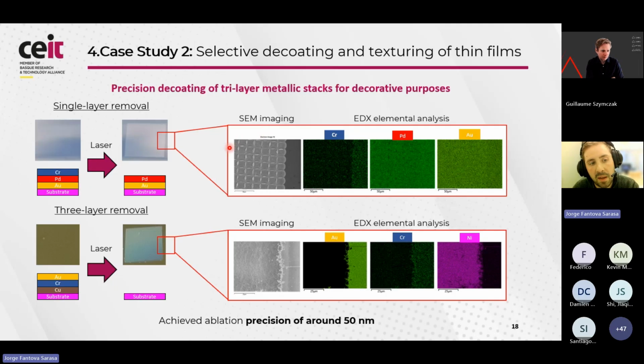And through this electron microscopy analysis, the imaging and the elemental analysis by EDX, in this case we achieve decoating of only the topmost layer, leaving the palladium and nickel layers unaffected. But you can have a larger removal, let's say.